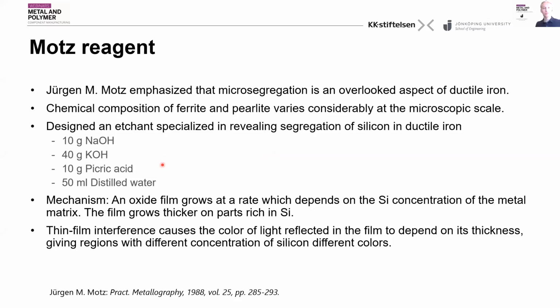Since silicon is often the most important element in cast irons, he designed a color etching method which was specialized in revealing the microsegregation patterns of silicon in ductile iron. The original composition was 10 grams of sodium hydroxide, 40 grams of potassium hydroxide, and 10 grams of picric acid, and then diluted with 50 milliliters of distilled water. The mechanism is that this etchant oxidizes the surface of the metallographic sample, forming a film. And the film grows at a rate that is dependent on the underlying silicon concentration.